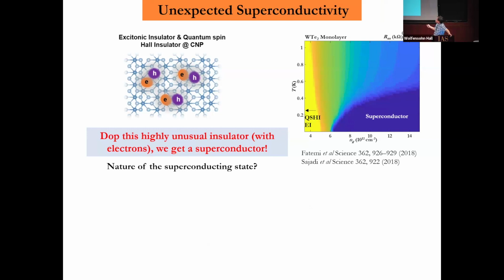This is related to doping the electron side, not the hole side. Dope to the hole side, we get a wide range of insulating states. Dope to the electron side, you quickly get a metallic state, and that metallic state becomes a superconductor. This was one of the very big surprises when we first saw this in 2017 - actually before the twisted magic angle graphene work. We found an interesting situation where you can gate-tune an insulating state with small voltage to a superconducting state, where the critical density of electrons is about 5 or 6 across different devices.